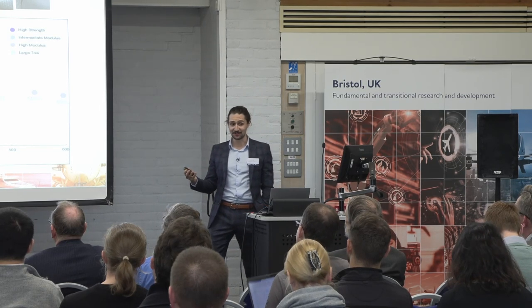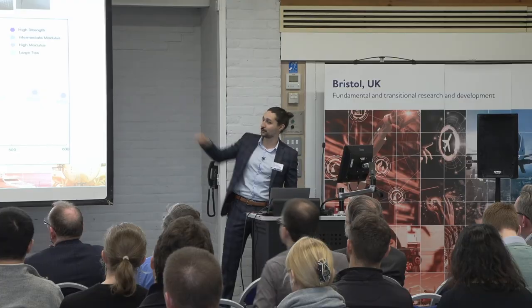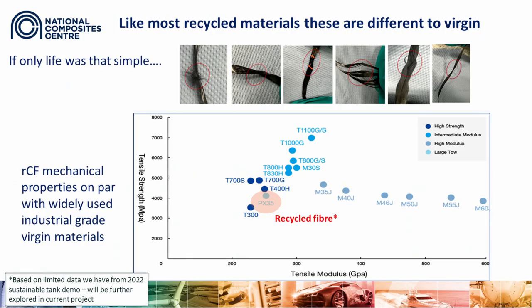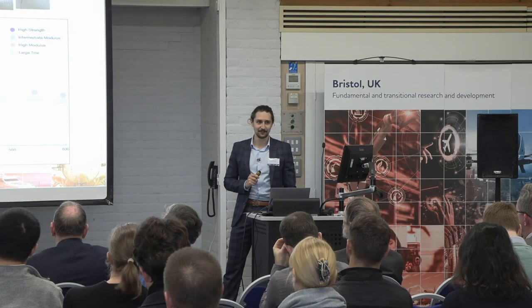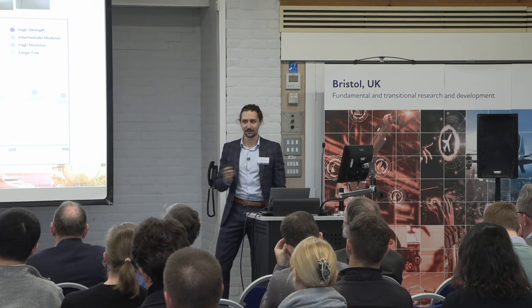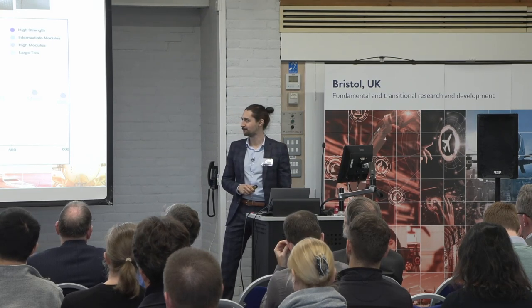These materials are not without their challenges, though. These are some images of the tows that we got from that unwinding. You can see a lot of macro scale defects on these tows, things like fluffing, twisting, and inconsistency in the tow width. Obviously, these are going to provide challenges when trying to handle these materials, made worse by the fact that there's no sizing on this. So all this combined is likely to jeopardize the performance of any secondary composites made with these materials.